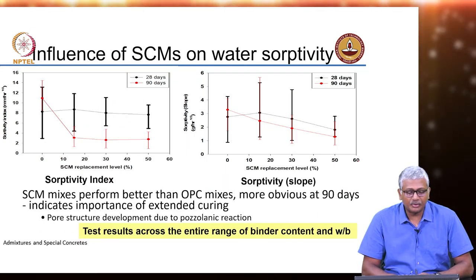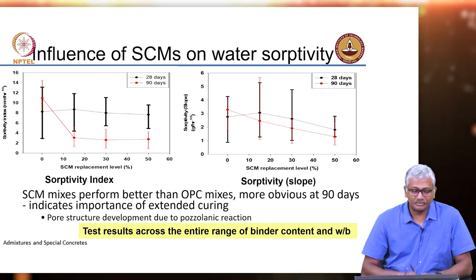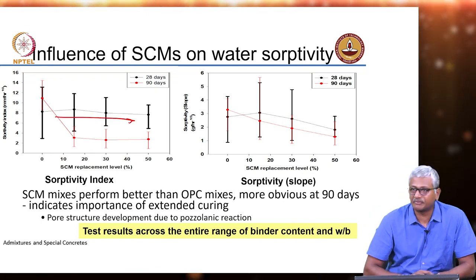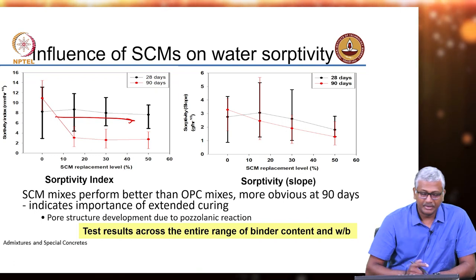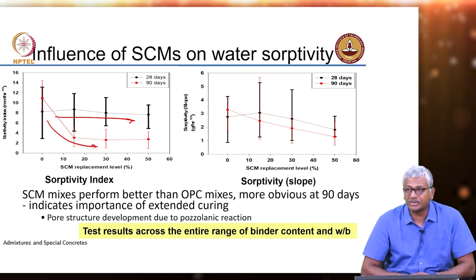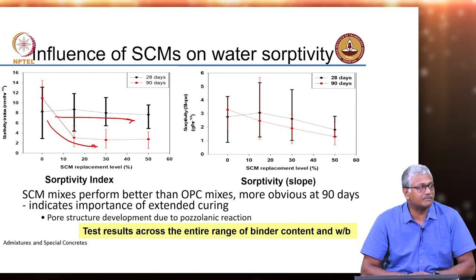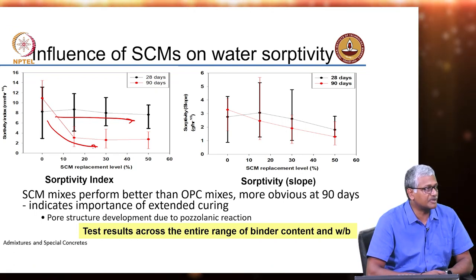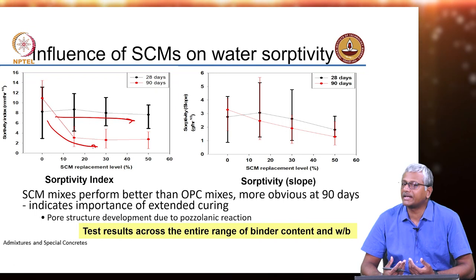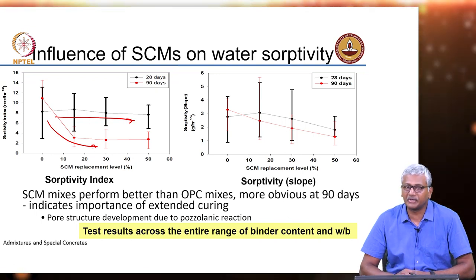The water sorptivity result also indicates that at 28 days there is not that much of a difference, but at 90 days you clearly see that the water sorptivity level is reduced when higher levels of cement replacement are done. Again, it goes to show the impact of extended curing on concretes with mineral admixtures.